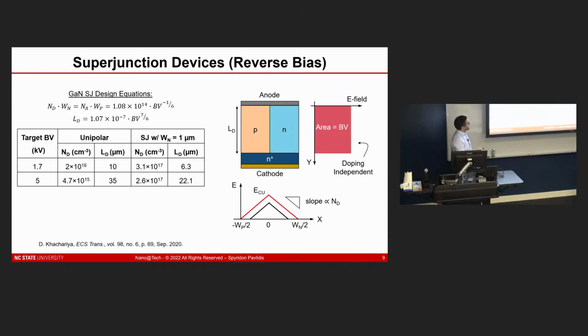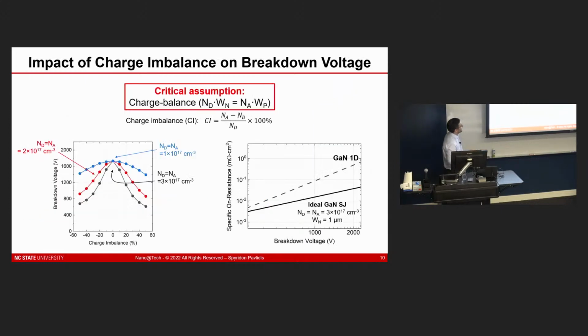So that relaxation in doping requirements means that we can do this with technologies that are available today, and devices can be made from a doping perspective alone. But the big problem that you'll see here is, again, how do I do that with selective area doping, right? So I can make an N-type region that has 10 to the 17 doping, yes, but how do I make these stripes side by side so I can make the superjunction work? So overall, those larger doping levels lead to smaller R-on and better efficiency.